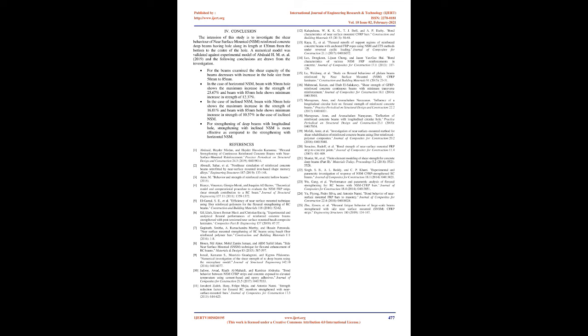For the beams examined, the shear capacity of the beams decreases with increase in the hole size from 50 mm to 85 mm. In the case of horizontal NSM, the beam with 50 mm hole shows the maximum increase in strength of 25.67% and the beam with 85 mm hole shows the minimum increase in strength of 12.37%. In the case of inclined NSM, the beam with 50 mm hole shows the maximum increase in strength of 16.01% and the beam with 85 mm hole shows the minimum increase in strength of 10.57%.